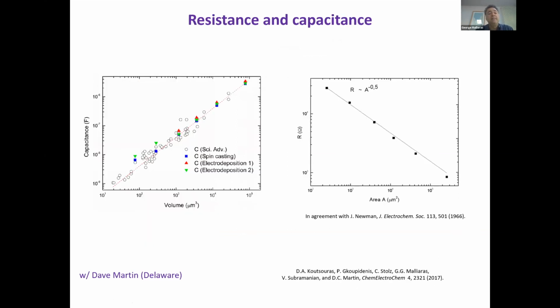If you analyze the data, then you get that the capacitance of the film scales linearly with the volume of the film, as you would expect from a textbook volumetric capacitor. This means that ions from the electrolyte get inside the P-dot film and distribute uniformly throughout this volume down to voxels of 10 cubic microns. The resistance scales with the perimeter of the electrode as expected due to the distribution of the electric field.